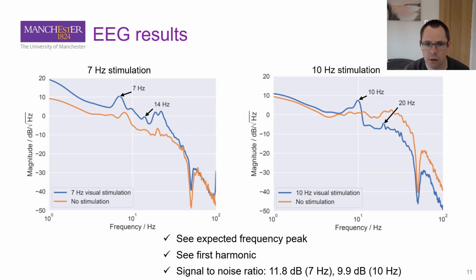So on the graph here, we've got power spectrums for when we flash the light at 7 Hertz and for when we flash the light at 10 Hertz. And we can see the expected peaks. We can also see a first harmonic of that stimulation frequency. And that's exactly what we would expect from EEG theory. Compared to when there's no stimulation present, in the no stimulation case, we don't see the peak, which again is exactly what we would expect. Comparing the difference between those 2 traces, we can measure the signal to noise ratio, and doing this over all of the different recordings that we did gives us an SNR of about 10 dB or so, so a good level of detectability.